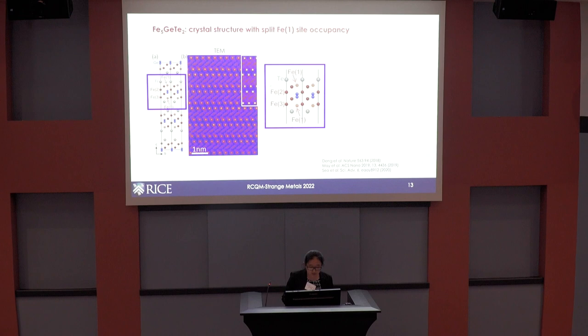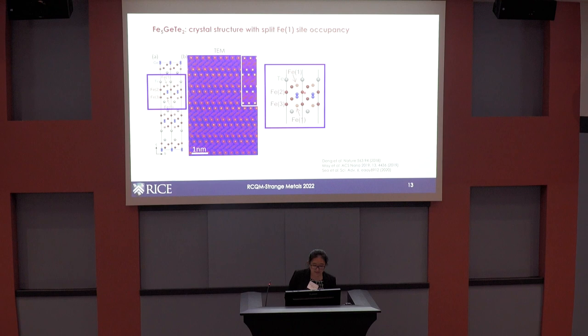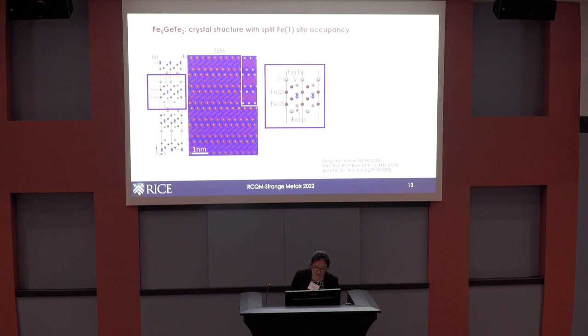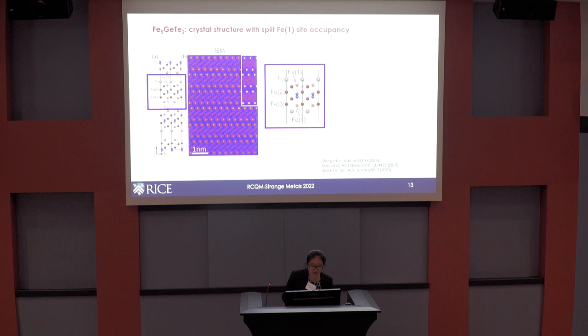The closest inversion-symmetric pair are the iron-2 sites, the next pair are the iron-3 sites — always fully occupied. The most interesting aspect is the last pair, the iron-1 site. For stoichiometric Fe₅GeTe₂, only one and only one of these two split sites is occupied at any given time. The iron-1 can only occupy either the upper or lower site within each pair, not both simultaneously.